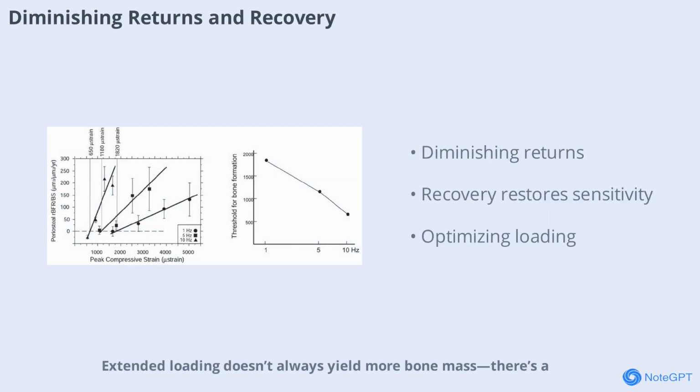Extended loading doesn't always yield more bone mass. There's a point of diminishing returns as bone cells become desensitized. However, introducing short recovery periods between loading bouts can restore mechanosensitivity and significantly increase bone formation. For example, a 4-hour rest between loading sessions nearly doubled bone response in animal studies. This principle is useful for optimizing training and rehabilitation schedules.